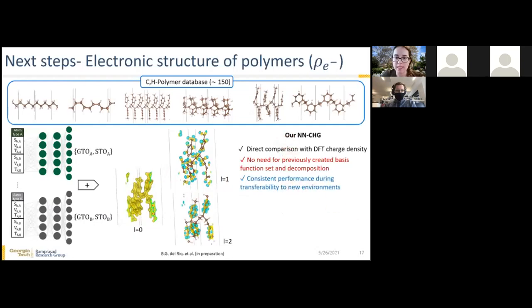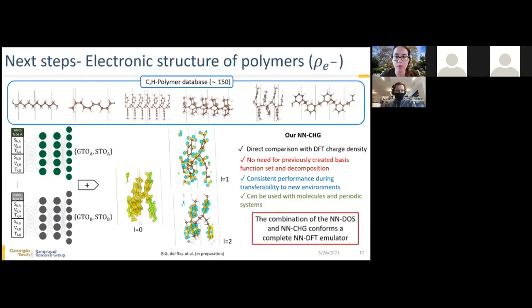Also, another thing to take into account is that we obtain very consistent performance. As I said, it's between 0.5 and 1.3% error. And that includes when we even test our model on crystalline polymers, which are not included at all in our training set. We only have chains. So it is a very robust and transferable model. And lastly, one thing that's very important is that it can be used with molecules and periodic systems alike, while the previous model by Fabricio and co-workers could only be applied to molecules. So together, once we combine both protocols, they can provide access to both the spatial and the energy distribution of the electronic structure and give us a complete neural network DFT emulator.